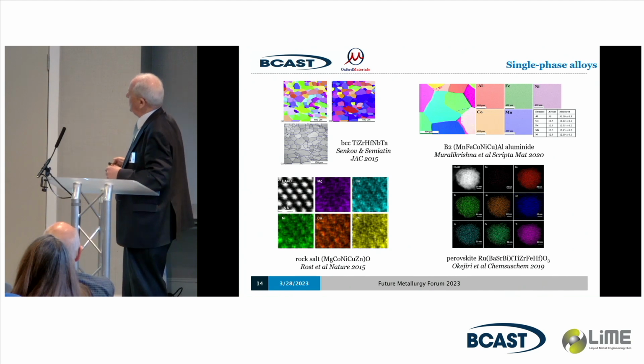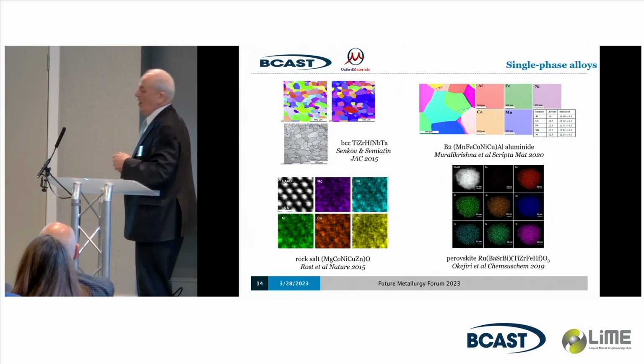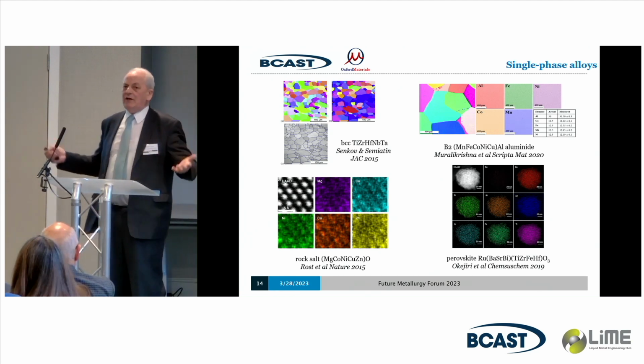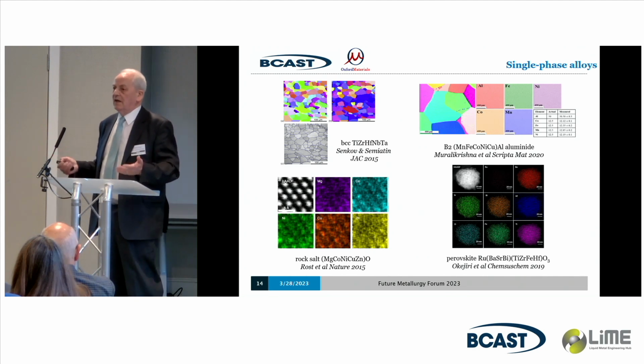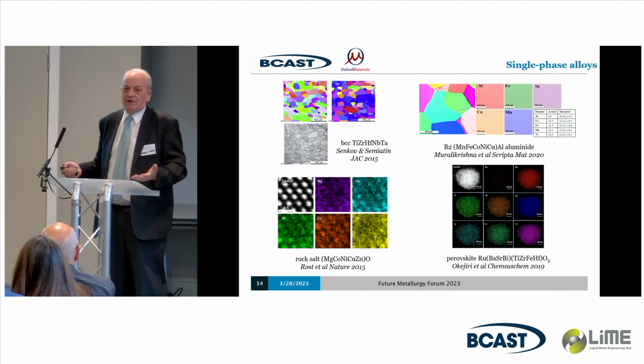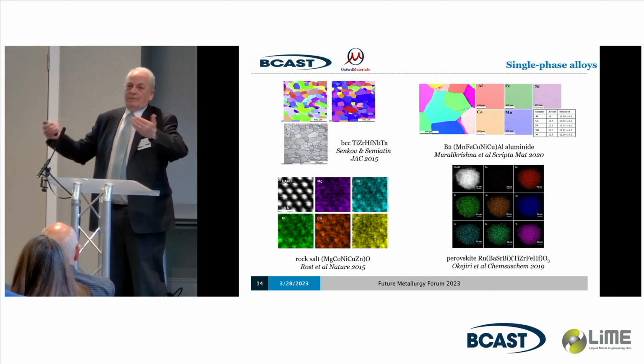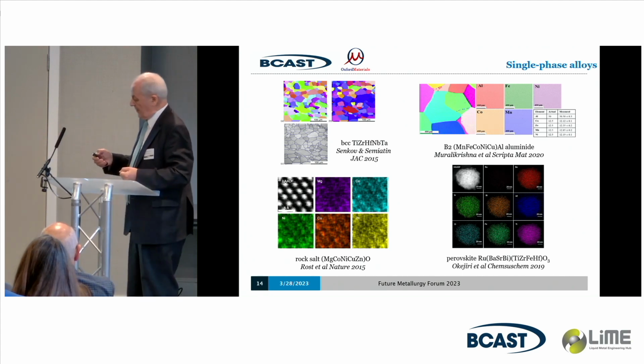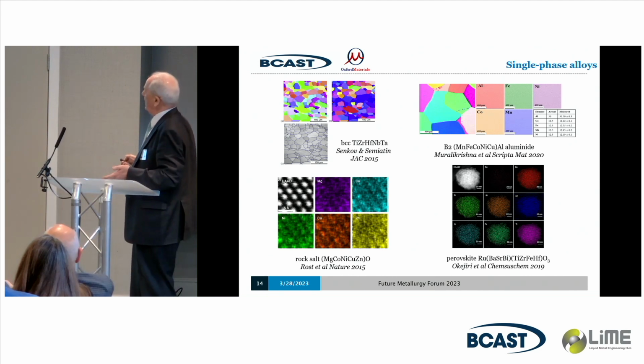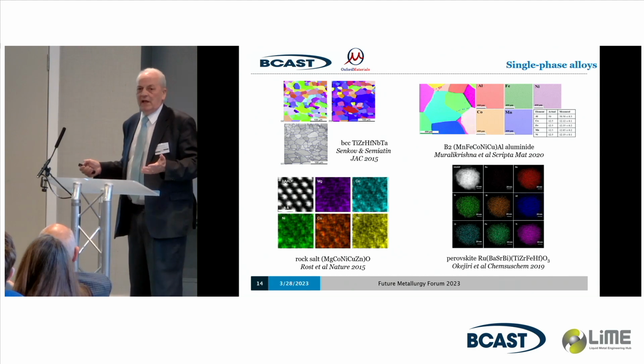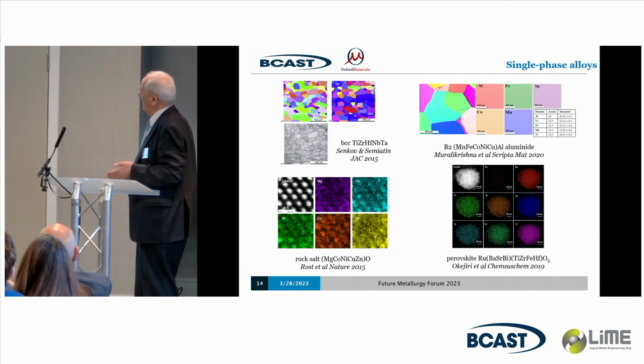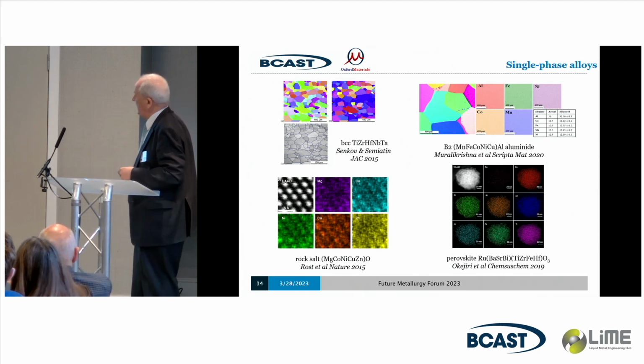This is a different 5-component equiatomic alloy. But you can see, again, the beautiful single-phase structure here. For most compound structures, it's the same thing. We now know something like 10 or 20 or 25 different crystal structures which you can randomize with multiple components on their single lattice or on one of their sublattices. So here is monoaluminide, MAL, with 5 different components. Again, perfect single crystal, incredibly ideal solid solution. Here, that's with the B2 structure, the cesium chloride structure. Here is a rock salt structure.